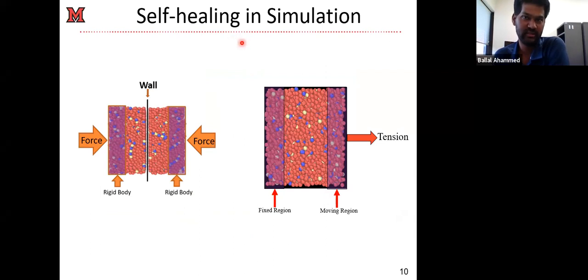In our case, the way we simulated the self-healing in our study is that we made two polymer parts, and first we placed an invisible wall between them. Then we defined two rigid bodies, and applied compressive forces on our systems. Then we removed the wall and allowed the polymer to heal itself, allowing some time. Depending on how much time you allow, we then apply the tension test to see how much it recovered. So to simulate this cut, we just replaced it with a wall and compressed it, in order to imitate the experiments.